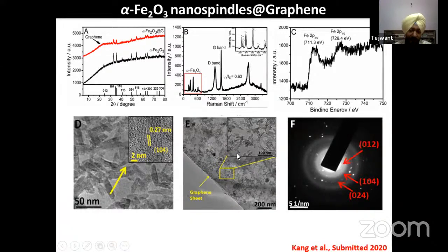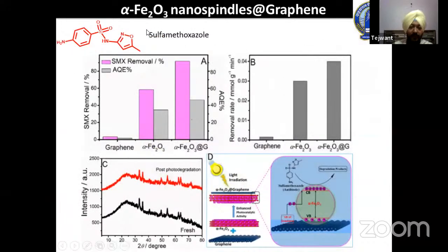So this composite has been used as a photocatalyst again for the photodegradation of another antibiotic, which is sulfamethoxazole. It has been found that more than 95% of the sulfamethoxazole has been removed from the aqueous solution within 2 hours of irradiation under visible light. When we compare the apparent quantum yield with graphene and bare alpha Fe2O3 nanoparticles, the prepared nanocomposite in the presence of graphene has shown the highest apparent quantum yield.